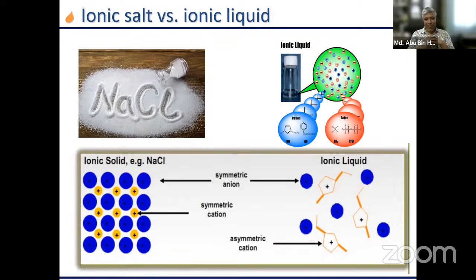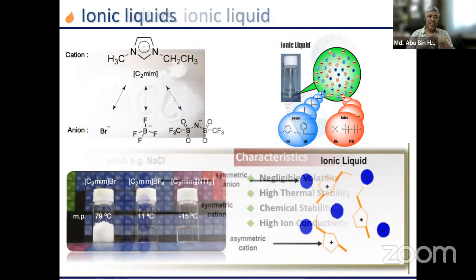So we can see sodium chloride. This is a stable salt. This has a very high melting temperature, we know. But ionic liquids comprise only ions, cation and anion, in combination like sodium chloride. This also has a combination of ions. But a symmetric anion and symmetric cation give rise to an ionic solid like sodium chloride with very high melting temperature. But here you can see that the cation is asymmetric. This asymmetric structure of the cation can yield ionic salts that are liquid at room temperature or even far below room temperature. Let us see the examples.